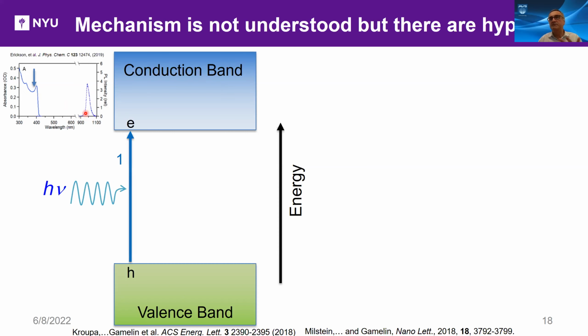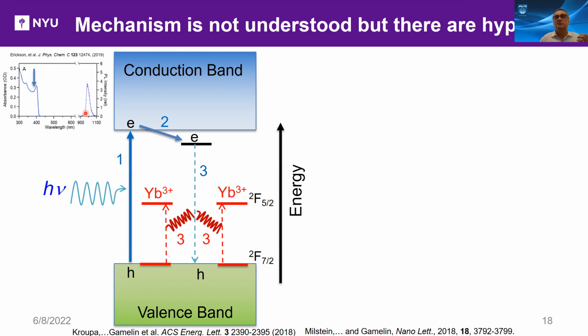The first step is to get the light to be absorbed to create an electron-hole pair. We think that the electron-hole pair, or electron, then gets trapped in a defect. And that defect is in close proximity of two ytterbium ions. Upon relaxation, it couples and transfers that energy to the ytterbium. So this is the band picture, the physicist view of how things happen.